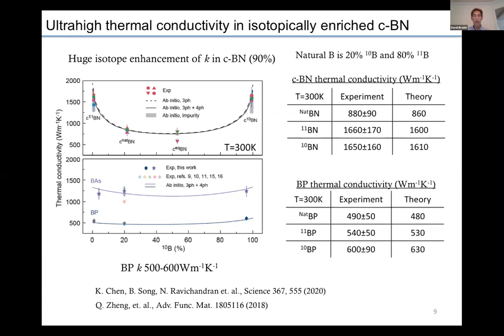So removing that isotope disorder gives dramatic increase in the thermal conductivity to exceptionally high values for isotopically enriched boron nitride. In boron phosphide and boron arsenide, shown in the lower plots, the enhancement is significantly smaller, although in boron phosphide, the thermal conductivity is enhanced from an already high value of 500 by about 20% to over 600 watts per meter Kelvin. So where does that leave us?